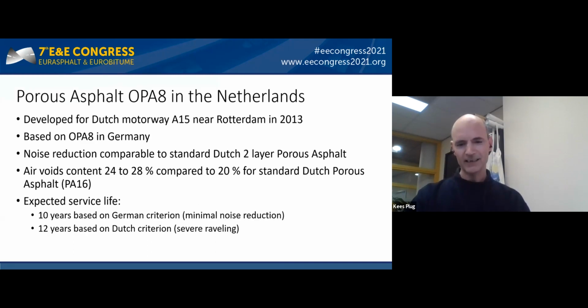Porous asphalt OPA 8 in the Netherlands is not a standard porous asphalt, but it was developed for the motorway A15 near Rotterdam in 2013. It was based on OPA 8 in Germany. The noise reduction is comparable to standard Dutch two-layer porous asphalt. And the air void content is 24 to 28% compared to 20% for the standard Dutch porous asphalt, which has not so high noise reduction. The expected service life is 10 years based on the German criterion, this minimal noise reduction, and 12 years based on the Dutch criterion for severe raveling.